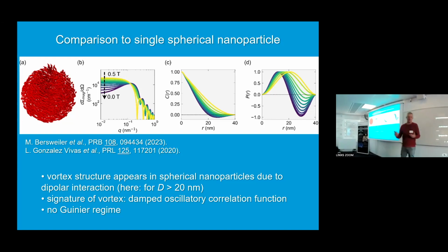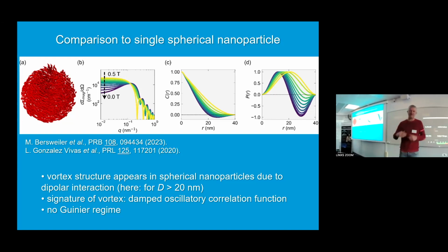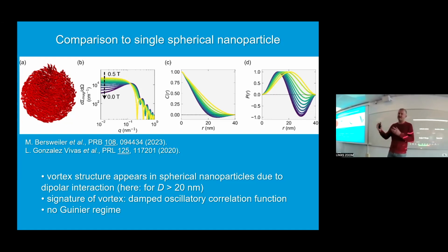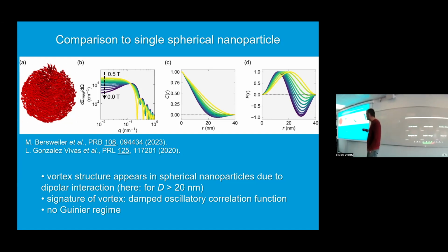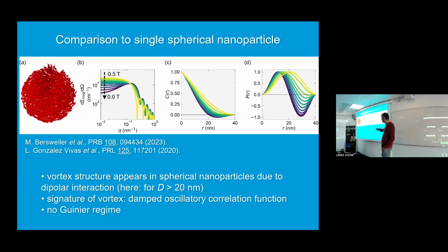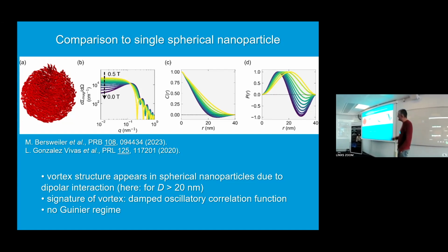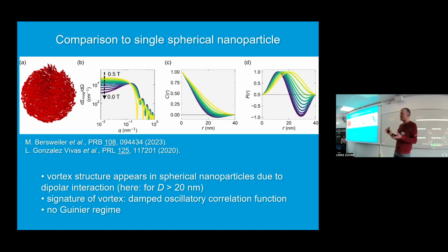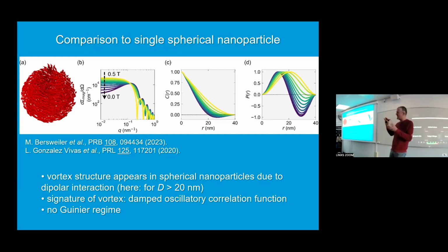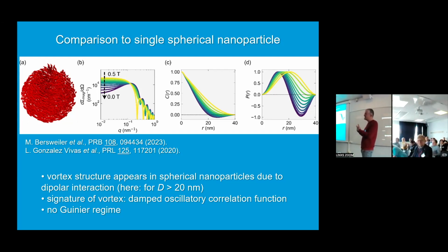I mean, you all know when you have small-angle scattering and you have homogeneous particles of different sizes, then the size distribution, of course, leads to a smearing, and you do not see these form factor oscillations anymore, you just see an envelope. But the very same thing happens here, because if you consider a sample that has different magnetic particles that are differently oriented, so each particle has a different orientation of the magnetic easy axis relative to the global direction of the external field, that means that each particle has its own magnetic energetics, meaning it has its own spin structure.